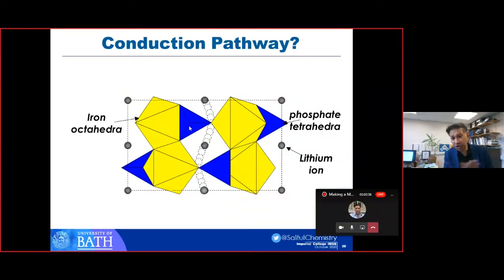So this is a slice through the structure. The iron octahedra are shown in yellow again. The grey are the lithium ions and the blues are the phosphates. So how do the lithium ions move? We predicted, from computer modeling, that it was a 1D conductor, a 1D channel, but not a linear path. It's a curved path. It's a bit like you and I, when we go hill walking, we don't walk in a straight line. We go by the lowest energy pathway, and this is the lowest energy pathway. It's curved. This was a clear prediction.